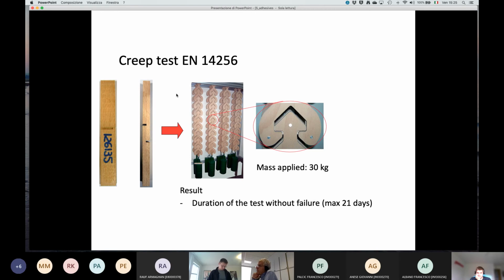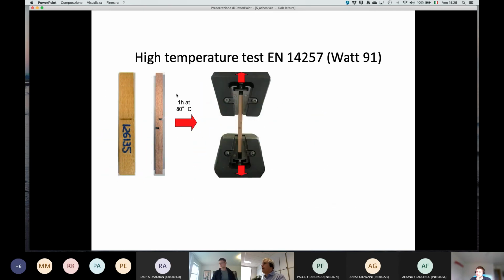And so now I think you know why this test is so important for thermoplastic adhesives, because of the possible flowing of the resin molecules because they are not bonded together. They are simply close to each other, and so the load can produce their movements with possible failure of the adhesion. So the creep test is a fundamental test for vinyl adhesive, for thermoplastic adhesives. There is also a test for the resistance to high temperatures. Again, it's important for thermoplastic adhesives to verify if they can resist at 80 degrees under load.